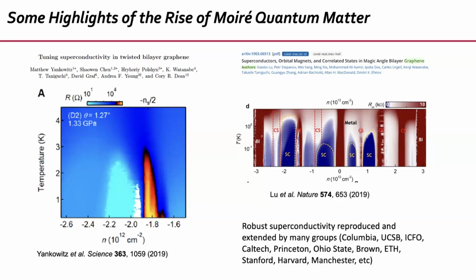But remember, this magic angle condition, this flat band condition, depends on the interlayer tunneling. So what they did is they applied pressure. When you apply pressure, the magic angle becomes a little bit larger. They knew which amount of pressure they had to apply, because together with Efthimios Kaxiras at Harvard, we had calculated already the pressure dependence of the magic angle condition. So they went to the right pressure, they cooled down, they measured, and they saw correlated insulators and superconductivity. Okay, so that was a very nice demonstration that indeed this physics is tied to the flat band condition, which is tunable by pressure.